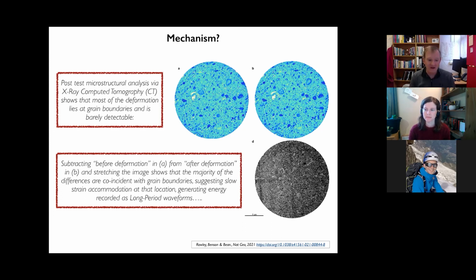So you've got kilometer scale fractures, and you've got hertz scale frequency data. So you can take this ratio, and if you do that, you get 10 to the 6 or something. Then apply that to field lab data, and it turns out you get exactly the same ratio.